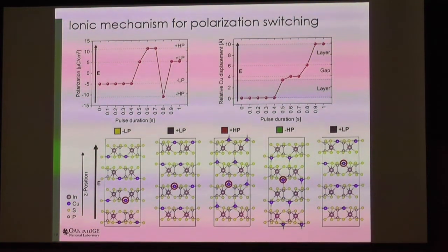You have four inequivalent sites, which have four inequivalent signatures in piezo, and therefore you know at which of your steps you are modulo 4. And you call that polarization state, but it's equally valid, what David is saying. If you would measure the charge which goes across, then your hysteresis loop probably would have 4 steps, right? Yeah.